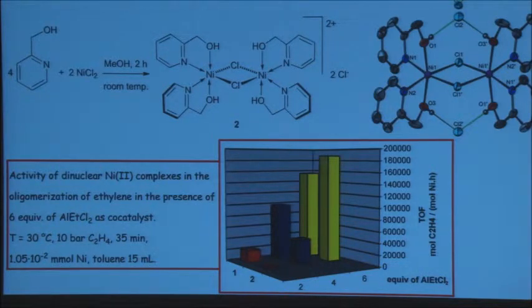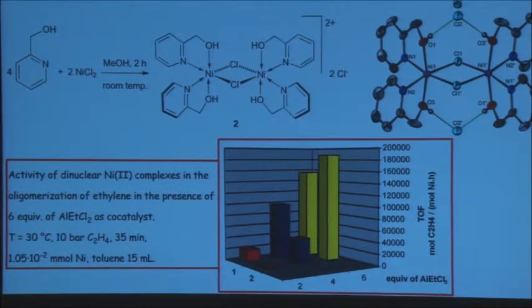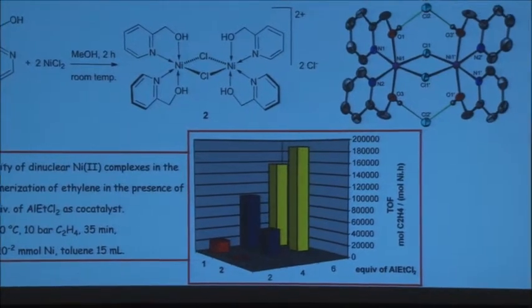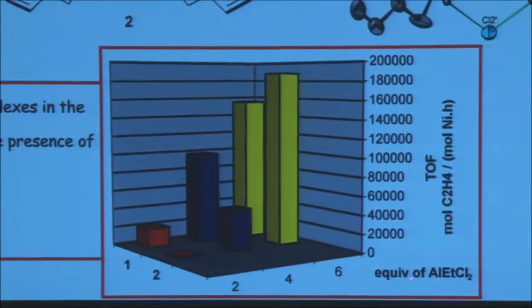These plots here show you the performances of catalyst 1, oxazoline-based, versus pyridine, catalyst 2, in the presence of 2, 4, or 6 equivalents of co-catalyst. And here we have the turnover frequencies, in other words, the number of times the catalytic cycle is operated per time unit. Here we have numbers which are quite high, 180,000. That's pretty good, so you can draw comparisons. You see that already with 6 equivalents, which is quite little, you get decent activities.